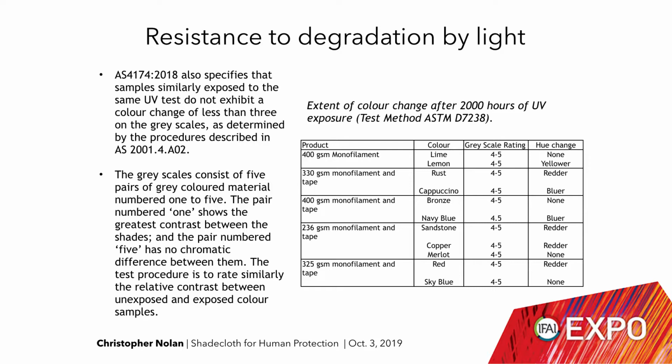Now the advantage, say what's the point of all this? Well, the advantage of this is you do get colour fading in material, and at least the standard now tells you what is acceptable colour fading. So in the event of supporting a warranty claim, for example, someone says this material has faded, you can very easily compare that to the grayscale. And if you have in your warranty saying we will meet this standard, then you've met the standard.